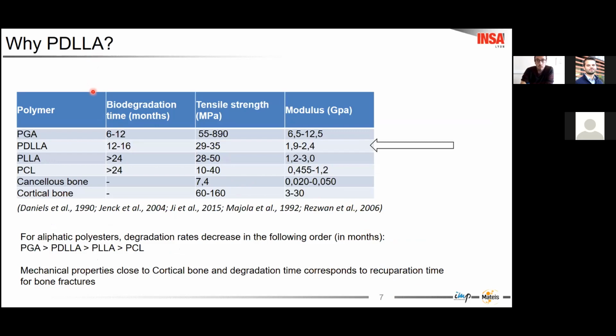In the family of aliphatic polyesters, PDLLA shows a low inflammatory response thanks to its non-crystallinity, and also has an interesting degradation time and mechanical properties close to those of cancellous bone and cortical bone. Here we can also see PGA, which degrades very fast and is inadequate for osteosynthesis. However, combining this PGA with PLA can modulate the degradation time of the polymer.